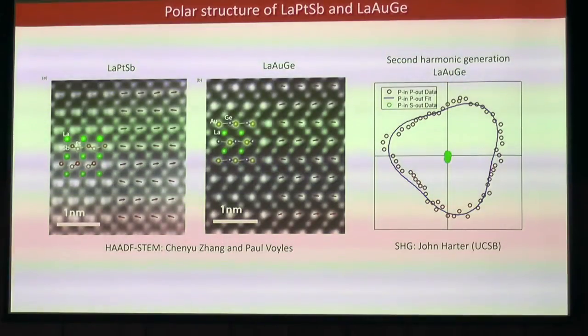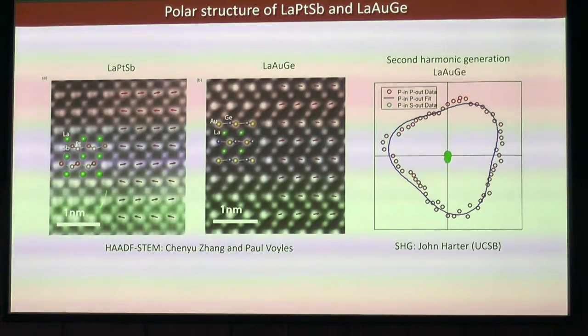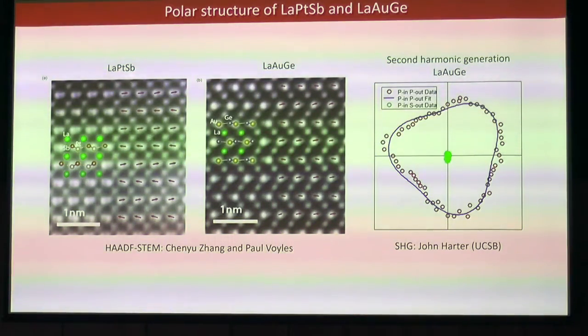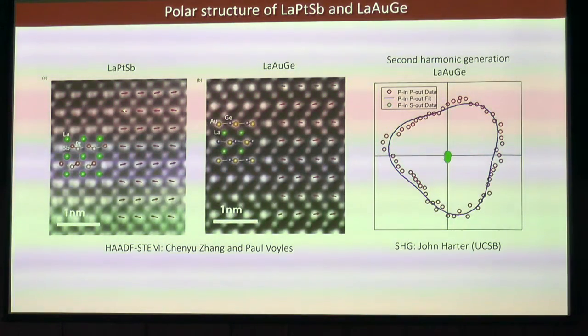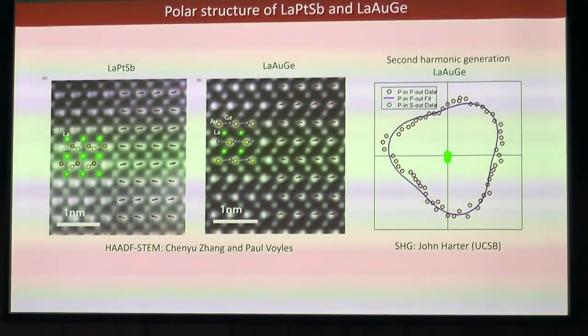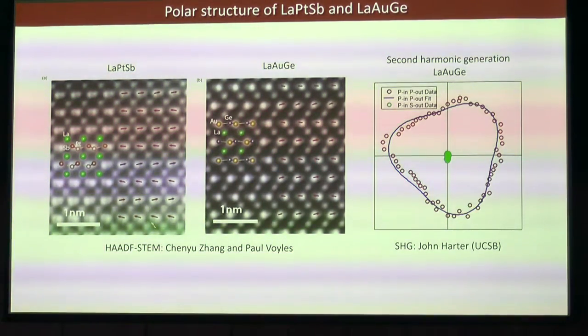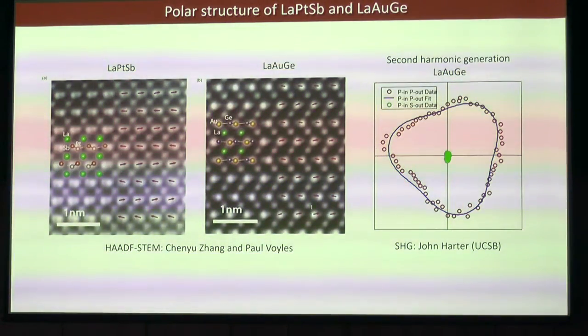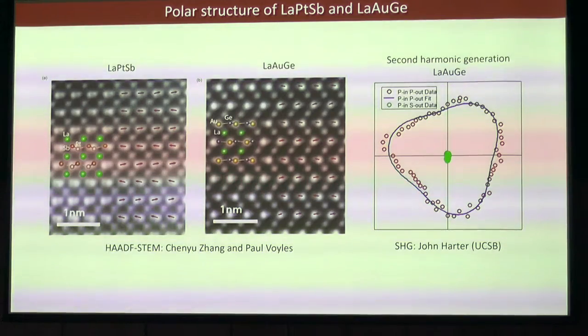Okay, so we can verify that we have the correct structure, and it's in fact the polar structure, by cross-sectional TEM. So here's the lanthanum platinum antimony. These arrows are sort of the center of mass for the antimony and platinum, right? So there's some long range structural polarization along the C-axis, as you'd expect. Same thing for lanthanum, gold, germanium. And by second harmonic generation measurements, we show that they actually are polar. Okay.